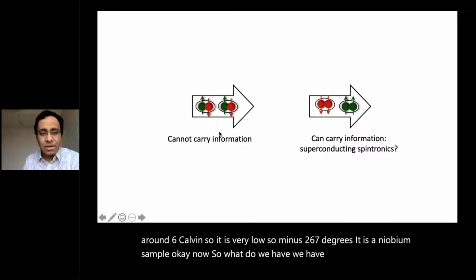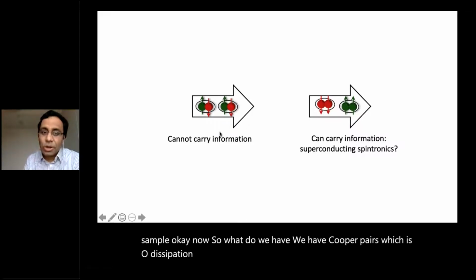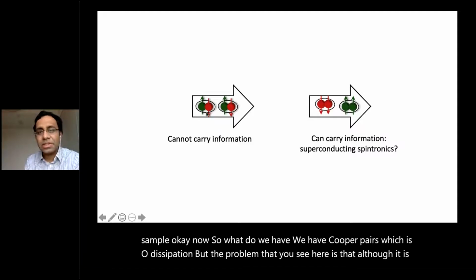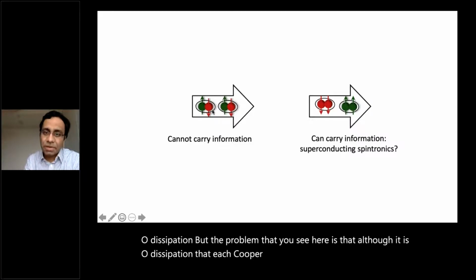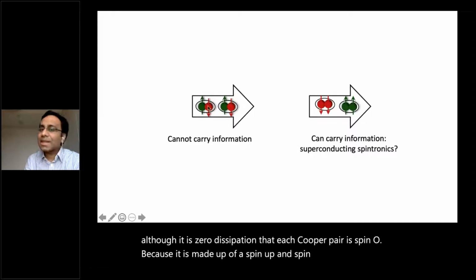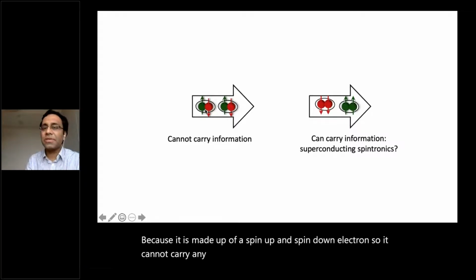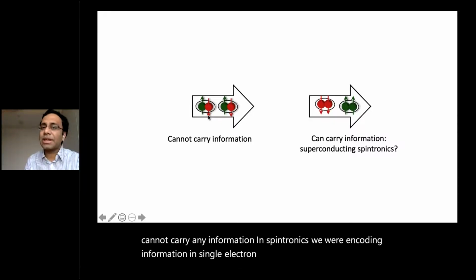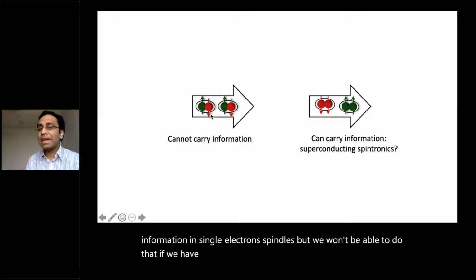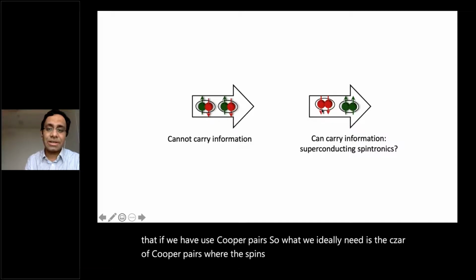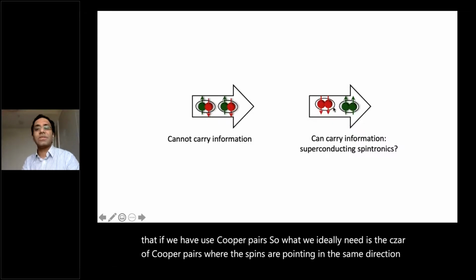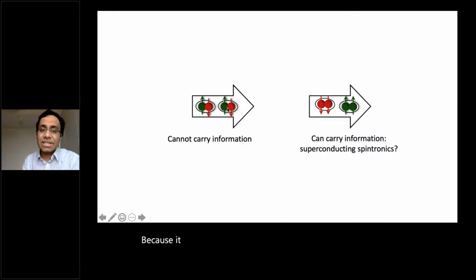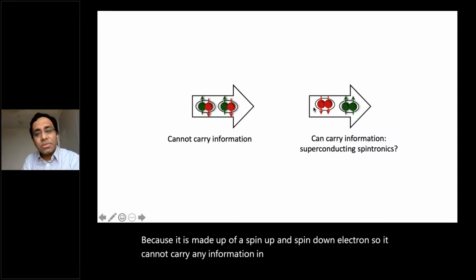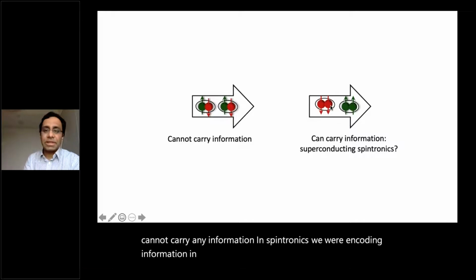We have Cooper pairs, which means 0 dissipation. But the problem that you see here is that although it is 0 dissipation, each Cooper pair is spin 0 because it is made up of a spin up and a spin down electron. So it cannot carry any information. In spintronics, we were encoding information in single electron spins, but we won't be able to do that if we use Cooper pairs. So what we ideally need is Cooper pairs where the spins are pointing in the same direction. In the language of quantum mechanics, this is known as triplet Cooper pairs, and these are singlet. So if we use triplet Cooper pairs, we can transmit information.